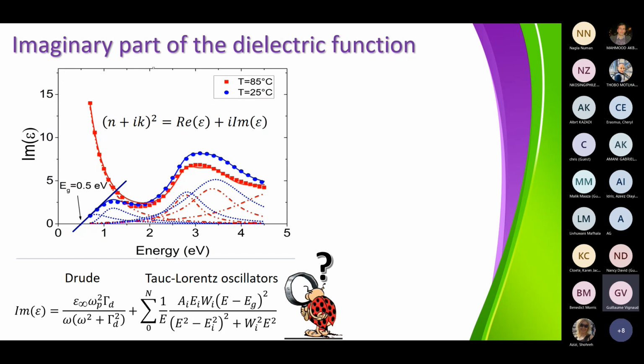Well, if it's in the metallic phase, you put the Drude component. And you can see the Drude component is this guy. So with a plasma frequency, which is omega p squared here, this is something which is related to the absorption, gamma d here. And this component is going to give you this tail here. See this one, this big tail is just described by this function.